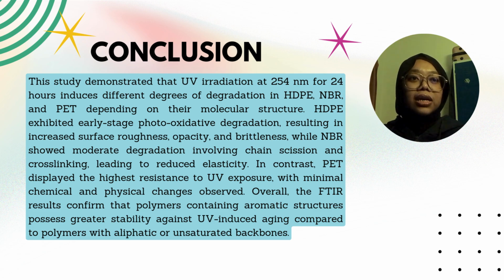Overall, the FTIR results confirm that polymers containing aromatic structures possess greater stability against UV-induced aging compared to polymers with aliphatic or unsaturated backbones.